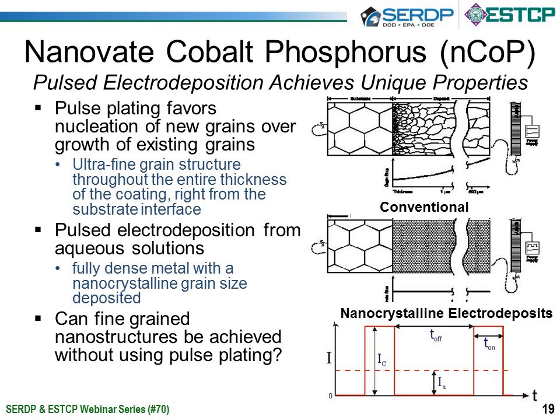So the way that we create our nanostructured materials is through a pulse electrodeposition process. Similar to chrome and nickel, it's made in an electrodeposition process. You produce the coatings in aqueous baths, you apply a current, and you deposit the metal ions in the solution onto your substrate in the form of a coating. Traditionally, we've used pulse electrodeposition in order to create the fine-grained structures.